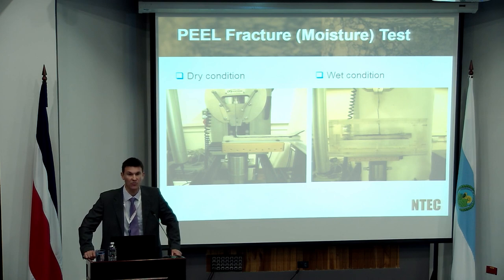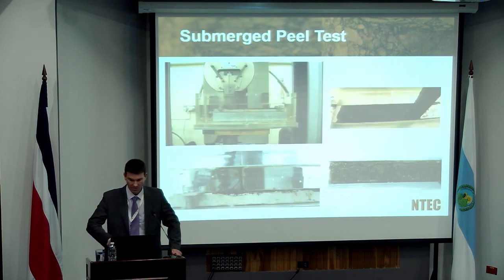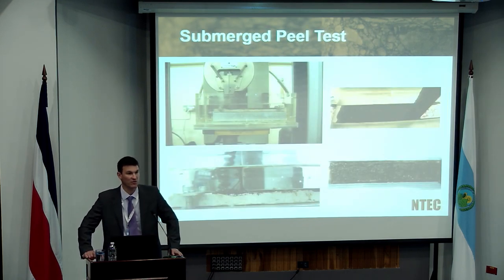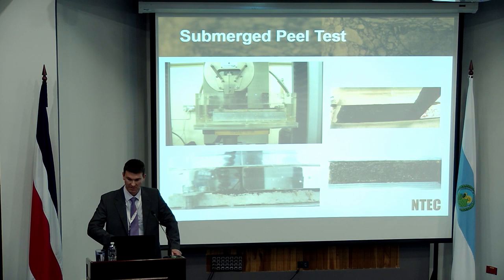The first one was to do the entire test inside a water bath or at least some kind of perspex chamber that allowed you to test the specimen in a moist environment. How does it work? Well, very simply, you take exactly the same geometry that you produced for the dry specimen. You will get a series of results, and the repeatability of this test is, it's all right, it's not great, but it's not too bad. We would then do a series of exactly the same specimen, but this time testing it underwater, and that would usually involve leaving the geometry underwater for anywhere up to 2 weeks at a time, and then doing the peel test.